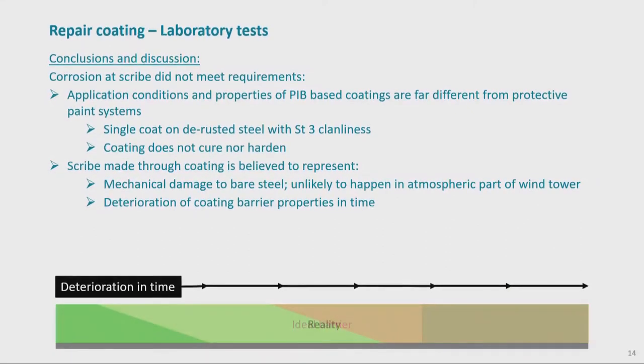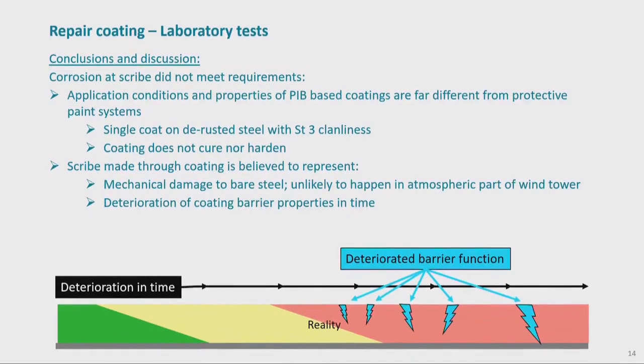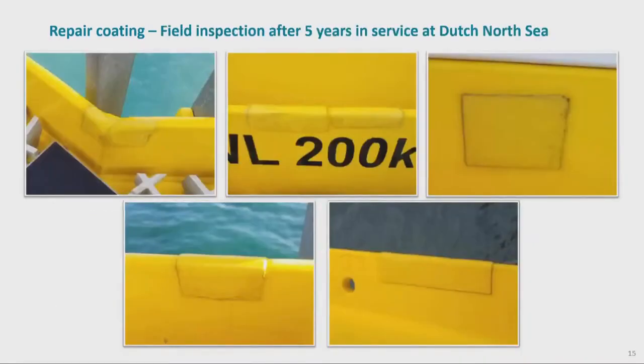And what we are really looking for is deterioration over time, which can be seen through coating breakdown factors, which is how long does it take for the coating to become permeable to the environment. And as we've seen in graphs, it's not a linear thing. It usually starts very slow, but when it really goes through, then you have an accelerated degradation with time, and then cathodic protection is there to take it over, or sometimes make it even worse. So that's the barrier function. And then you have a corrosion, and then you go in.